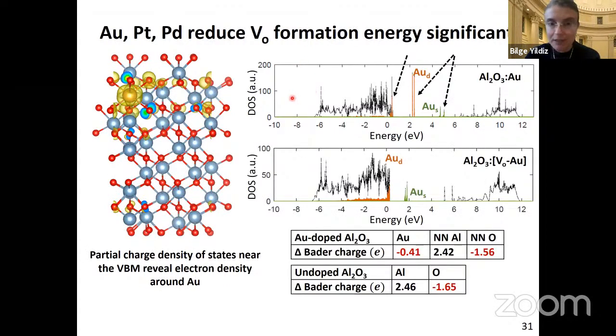So what else do we see here? What is gold really doing? When we insert gold into alumina, by looking at this electronic density of states, we can see that gold is introducing these in-gap states that, when you form an oxygen vacancy, can pick up the electron left behind and lower the state energies. And we can see from the charge analysis that gold, once you create an oxygen vacancy, picks up electron, or even without the oxygen vacancy. So gold picks up electrons, it becomes negative, and this electron comes both from the aluminum and oxygen, which become less in charge compared to the undoped case.